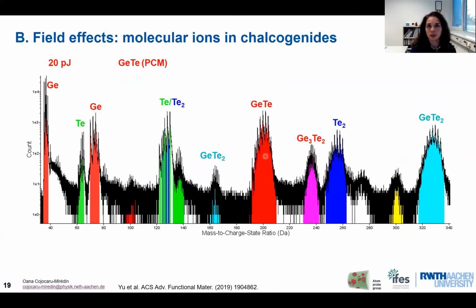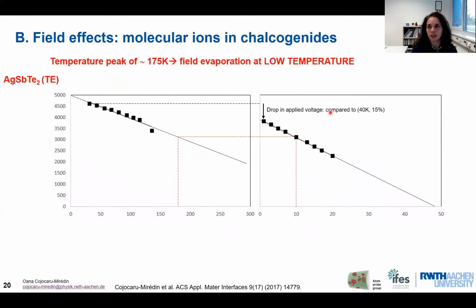And the third example is a GeTe compound. This is a phase change material used for memory applications. For this compound, we have the same: on the right-hand side, a huge amount of molecular ions present on the mass spectra. The total number of these molecular ions is about 45%. So for all these three examples, we can see that we have a pretty high proportion of molecular ions, and this cannot be avoided by applying different parameters during the atom probe analysis. Of course, we can change the fraction of them, but they cannot be avoided at all on the mass spectra.